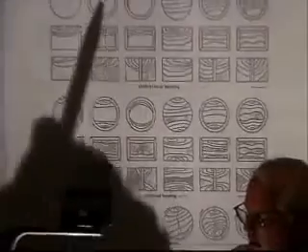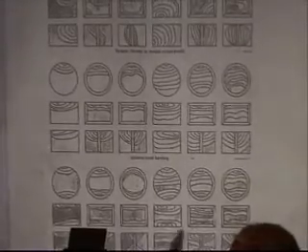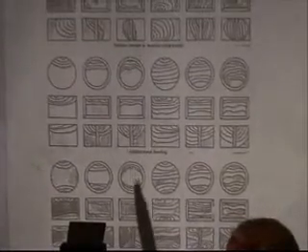Okay, so you're either pulling on it, bending it, twisting it, or bending it back and forth. Well, if you're bending it back and forth, you should get a fatigue crack that starts on both sides, because you're going both ways. If you're only doing unidirectional bending, if it's just bent down and comes back up, then you're only going to get a fatigue crack starting on one side. So if someone brings you a broken bolt, you ought to be able to see whether there's a fatigue crack on one side or both sides. If it's on both sides, then it's reverse bending. If it's a fatigue crack and it's only on one side, then it could either be bending or it could be tension. So it could be either a tensile stress from bending or a tensile stress from pulling. However, you can then look at other features of the part.